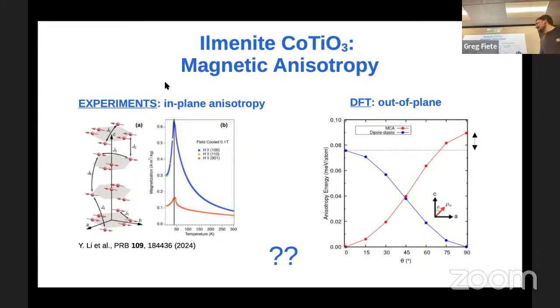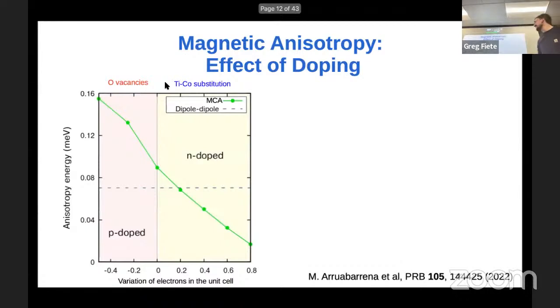We had many discussions about this, and we finally did the following, which was analyzing the effect of doping on the system. And we did it by considering two different kinds of doping. First of all, we consider oxygen vacancies, which is equivalent to having some oxygen sites not filled with oxygen in the compound. This is reasonable for oxides, it happens.